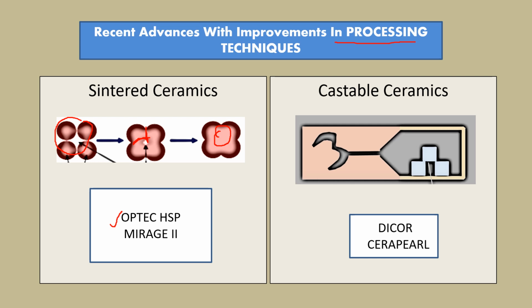Then moving on to the castable ceramics, this is done in a fashion similar to the conventional lost wax technique, where a die is prepared from an impression and a wax pattern is fabricated, and this wax pattern is then invested. This is then subjected to the burn-out procedure and followed by loading in a centrifugal casting machine. The ceramic blocks are then loaded in the crucibles and the casting procedure is executed. The examples are Dicor and Cerapearl.